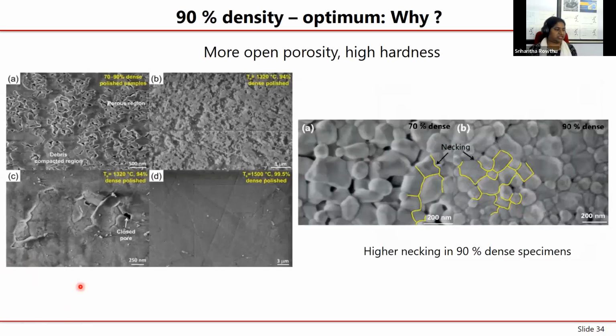So let's see why that is the case. So the reasons are the following. As we are changing from 70% density to 99.5% density, what is happening? Definitely there is grain growth after 90%, but from 70% the porosity is already decreasing. And these are the factors, right? For example, in the case of the 90% dense sample, your amount of open porosity is quite high, so that will help the lubricant to replenish on the dry surfaces.